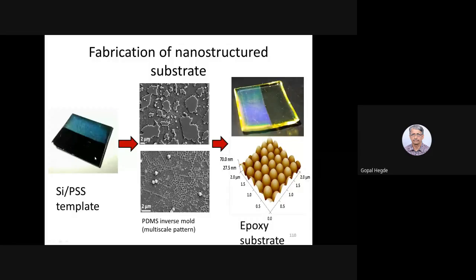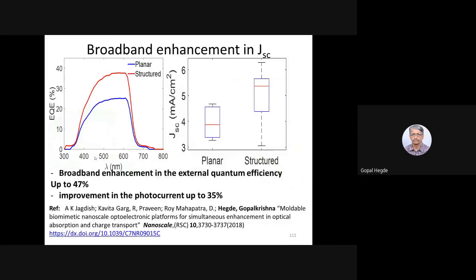Then on the silicon, we made this template, and we did all the photovoltaic structures, whatever we wanted to do, and we saw a broadband enhancement in the external quantum efficiency. The increase was about 47%. You see, this is the planar structure, and this is the structure. Okay, nanophotonic structures, that means it's a lens structure. At the same time, current density was also increased in the structured one compared to the planar one.